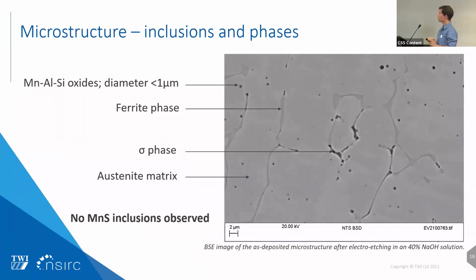We can also notice the presence of small oxides visible here, all the dots here. Those are silicon rich, and you can also find other elements such as manganese and aluminium. This is perfectly normal; it's due to the fact that we're using a welding wire with a larger amount of silicon to act as a deoxidizer during the deposition.